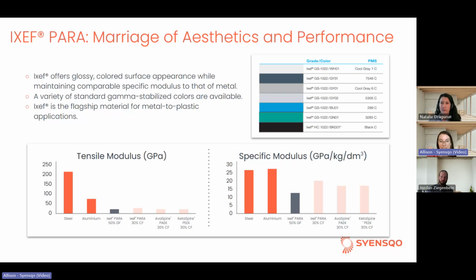So again, Ixef is our main material for metal to plastic replacement, and it's evidenced at the bottom right graph, which is a graph for specific modulus. When considering the stiffness of XF versus metal from a pure modulus standpoint, it does look obviously like metal has a much higher stiffness and a much higher modulus. But when you compare stiffness for the density of both the metal and the Ixef, you'll see that XF, for its density as a polymer material, can have a comparable modulus to that of metal.